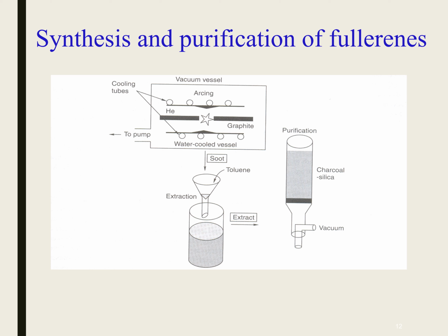And the purification of fullerenes is related to this schematic illustration of the process involved in the synthesis and purification of fullerenes. Graphite rods are evaporated in an arc under a helium atmosphere. The soot collected is extracted with toluene and subjected to chromatography.